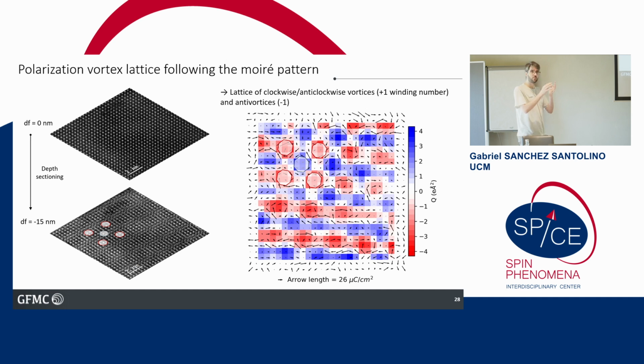So due to this twisting of the layers, in the top layer we are going to have these ferroelectric structures, which in this case are very, very small structures, just about 6 unit cells in size, of polarization vortices that are going to be rotating clockwise, anti-clockwise, clockwise, anti-clockwise, forming this lattice of vortices and anti-vortices.